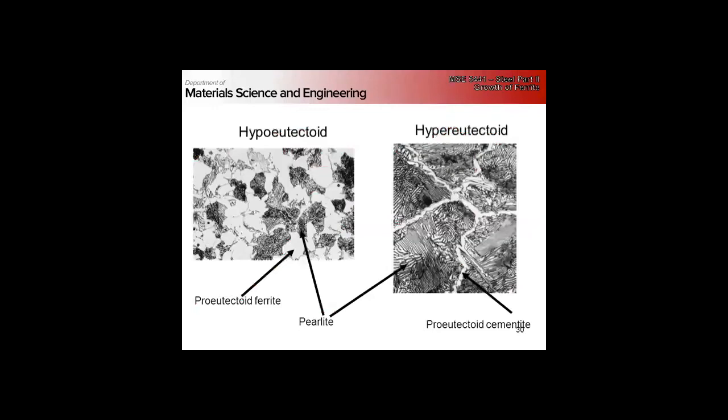So I noticed that both ferrite and cementite form at grain boundaries, but their morphology is different. Why is ferrite more like a...? Well, they're different. Ferrite is metallic, and cementite is a ceramic material. It's intermetallic, so their chemistry is quite different. Their surface energy with respect to the austenite is going to be quite different.